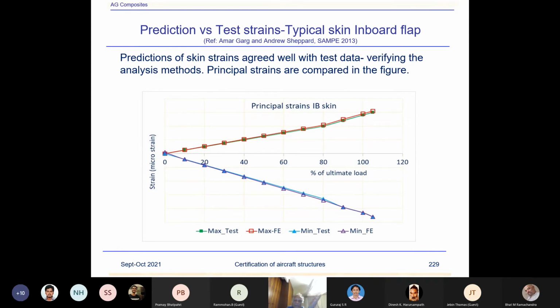For the structure, you are analyzing a larger structure, and how the skin strains behave could be quite different in your analysis than in test. Right. So what happened really during the analysis and testing program? We got the test data, and test data in some locations deviated by more than 5% from the required agreement between the test and analysis. So then it had to be analyzed.